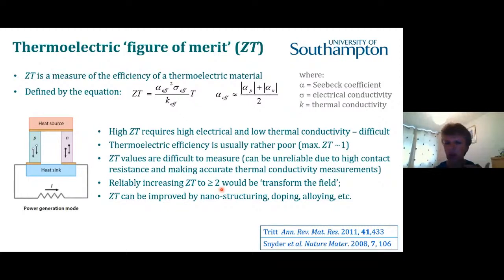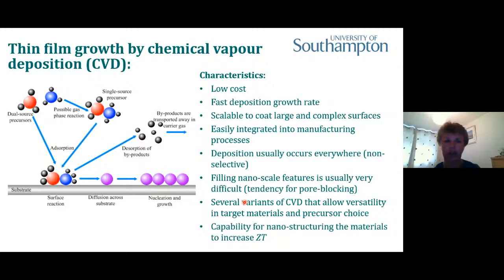And one of the strategies, it's not what I'm going to be talking about today, but one of the strategies to do that is to undertake nanostructuring of the material, to dope or alloy the material with other elements to optimize these properties. So that's just a little bit of background to why these materials are of interest in the application area. In terms of the growth method that we're using here, if we want to grow thin films, there are a number of ways that thin films can be grown, but chemical vapor deposition is one of the most widely used techniques.